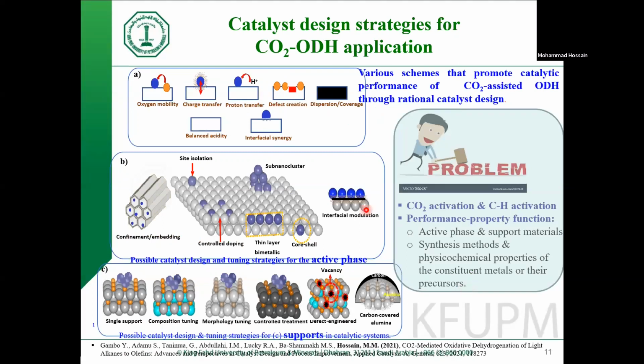Now, in order to achieve this, one can think about the catalyst design. In catalyst design, there could be alternative approaches to secure the desired mechanism in order to get the selective product. And always the target is to activate CO2 and the carbon-hydrogen bond of the hydrocarbon. All this can be achieved by using an active phase and support. So there will be two components. One is the active phase, which is metal, and the other is the support, which can be alumina, silica, and so on. Of course, the synthesis method, the precursor used, and the subsequent treatment also play a major role in the selectivity of those catalysts towards a desired product.